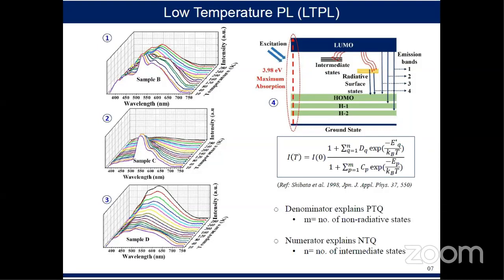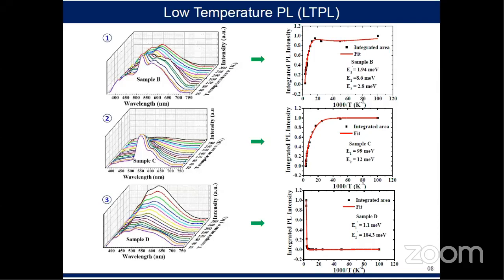The NTQ and PTQ characteristics can be explained using this equation by Shibata et al, where the denominator explains positive thermal quenching and the numerator explains negative thermal quenching. So next slide. Using this equation, we can fit the integrated PL intensity with inverse of temperature to see the exact NTQ, PTQ characteristics with the extracted activation energies of different radiative and non-radiative states.